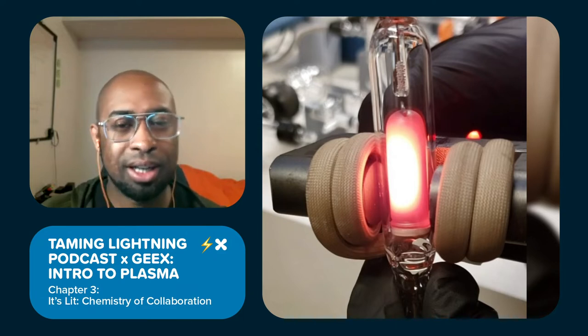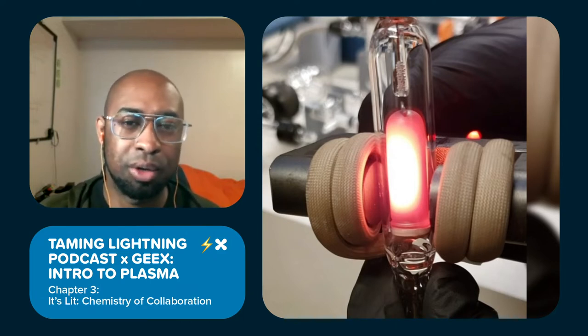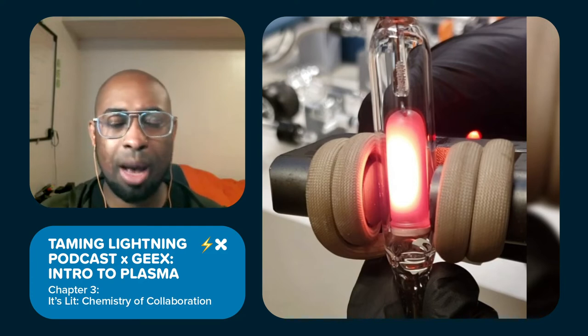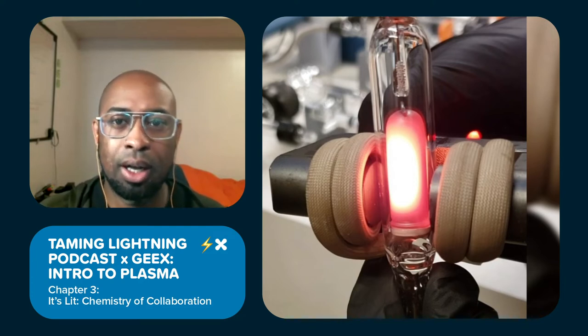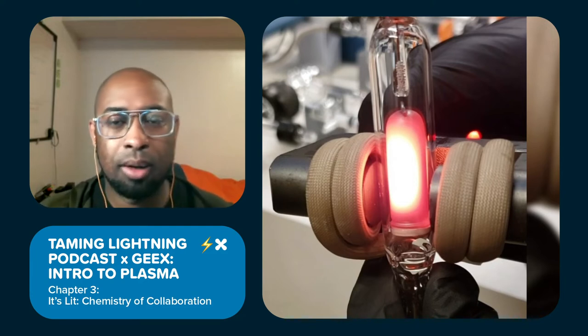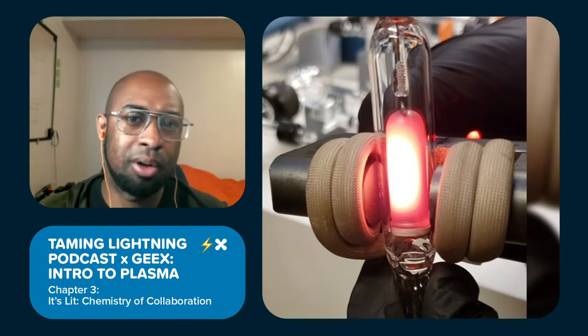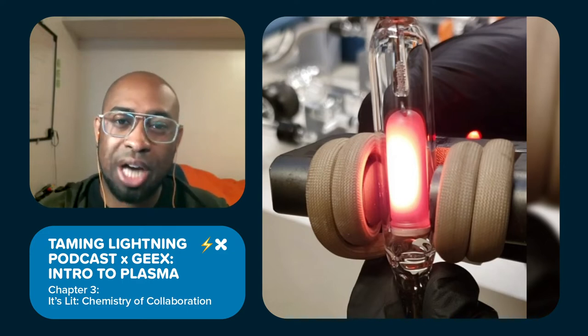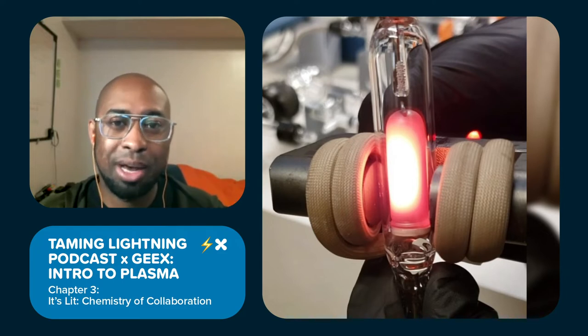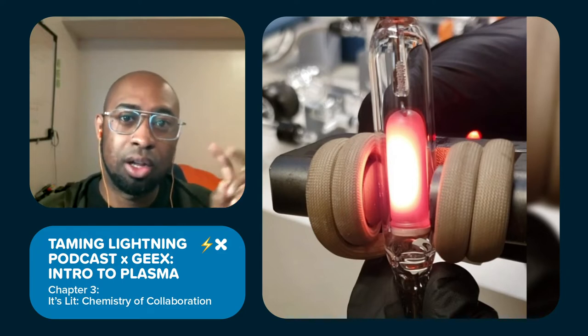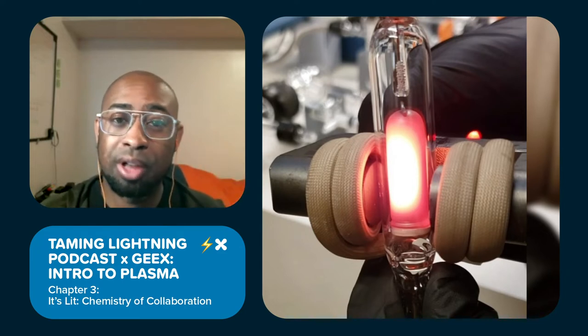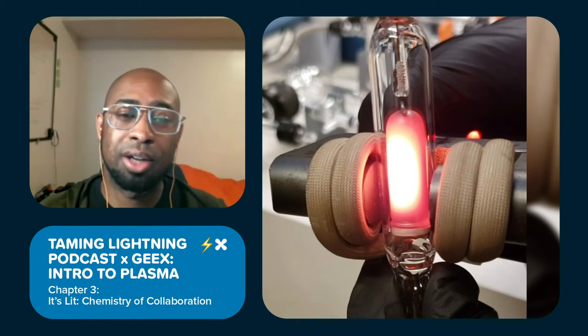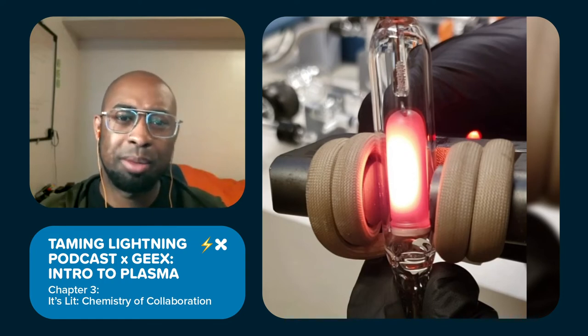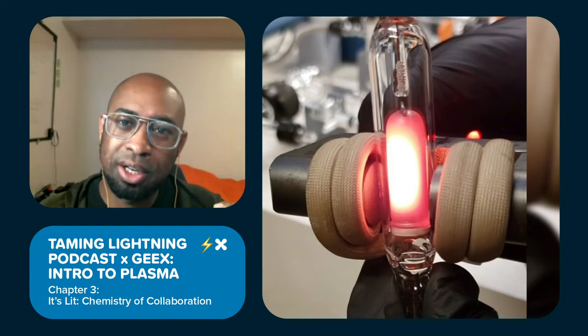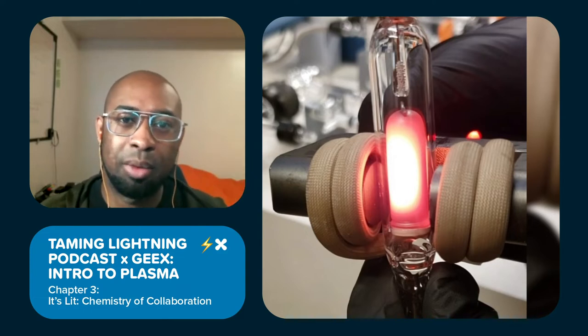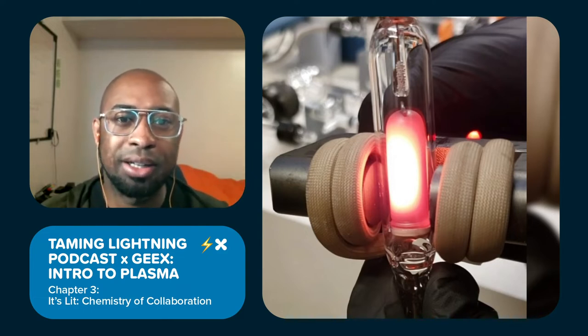Now, before you even go to the next step, you have to let that area cool down. There are some risks that have been discussed among a few other plasma makers, and that involves the possibility of thermal shocking your glass from having that heated metal shell inducing a lower, colder temperature gas into that area and causing thermal shock. So make sure it cools down just enough that you can touch it and it doesn't seem too hot.